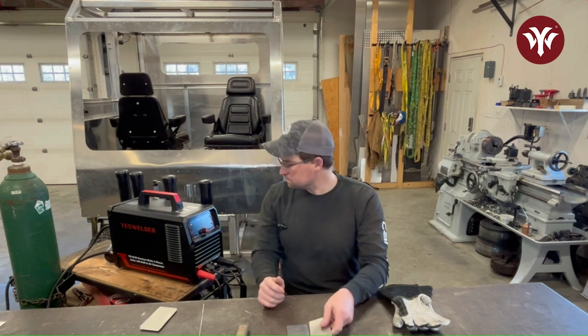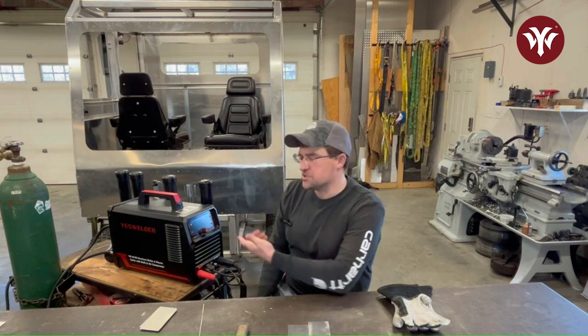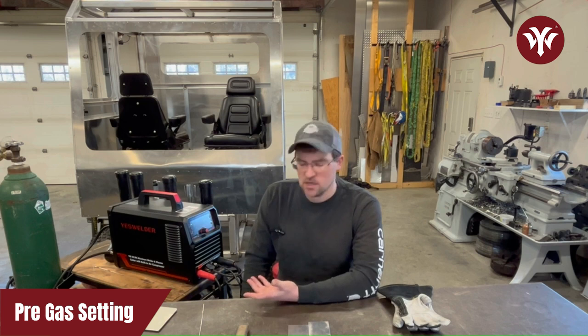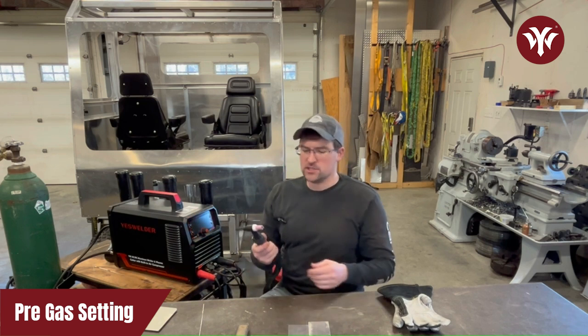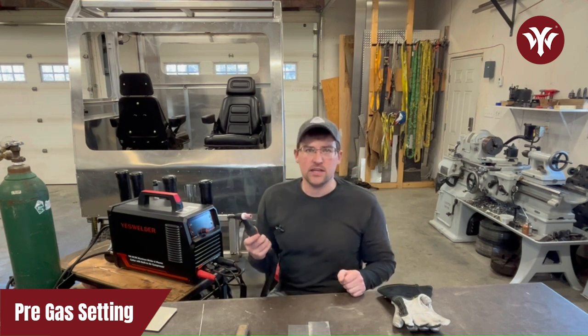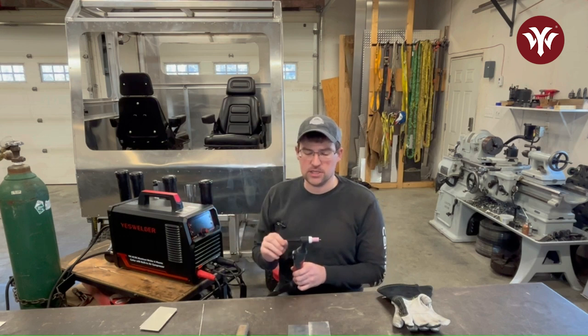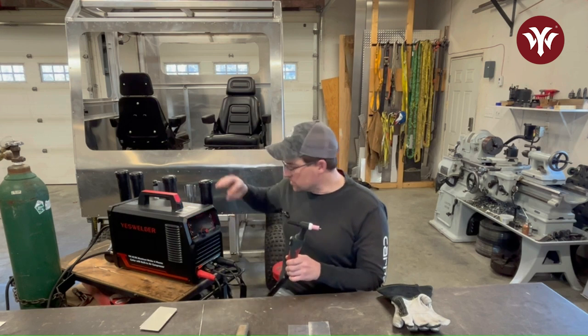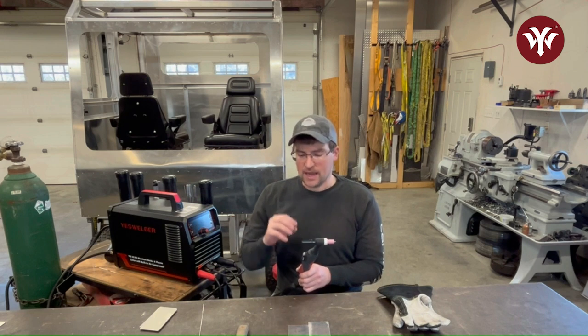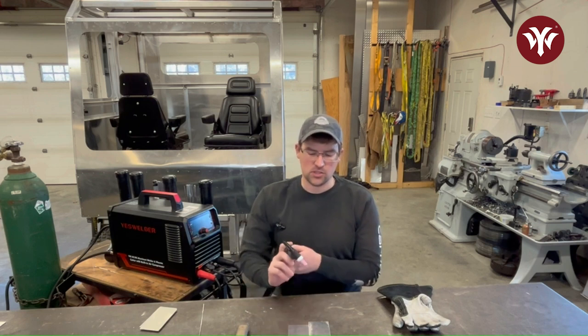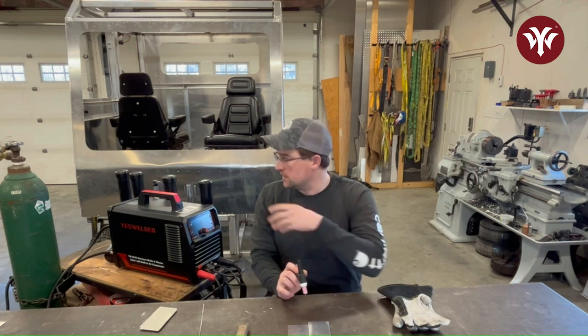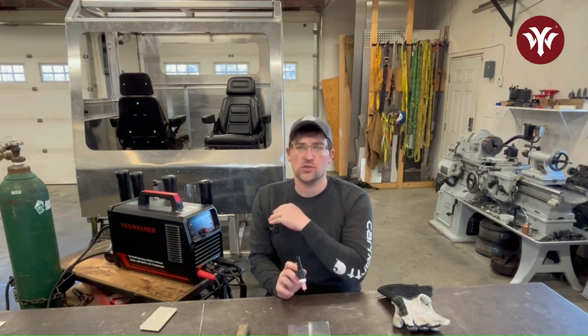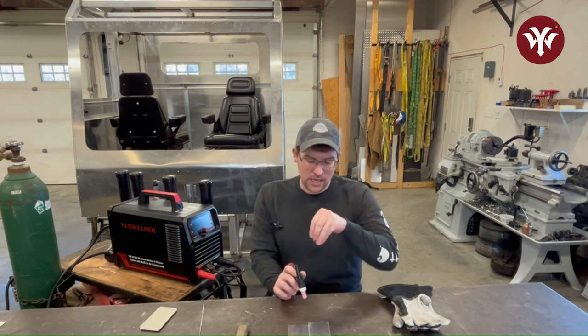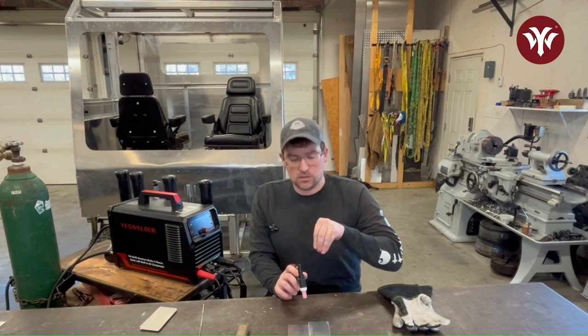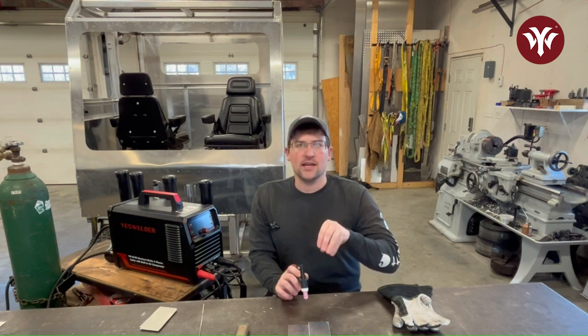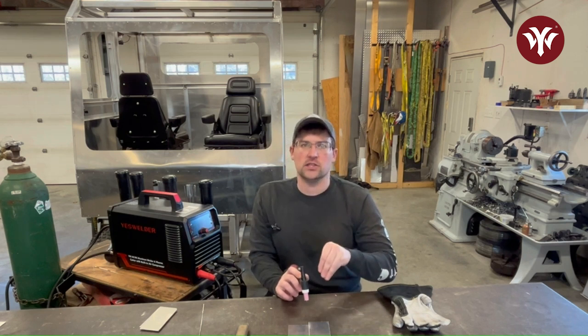One of the other settings you're going to see come up on here is pre-gas. Pre-gas is the amount of time between when you initiate an arc start on the machine, it's going to flow gas through your torch, and then the arc will start. That's to ensure that you have argon. In this case, since we're welding aluminum, we're using 100% pure argon. It's going to ensure that when that arc fires and starts, it's doing it inside the shielding gas, in an inert environment.